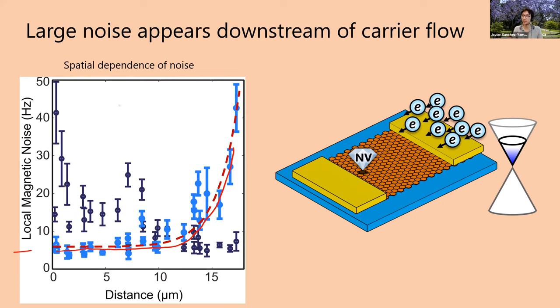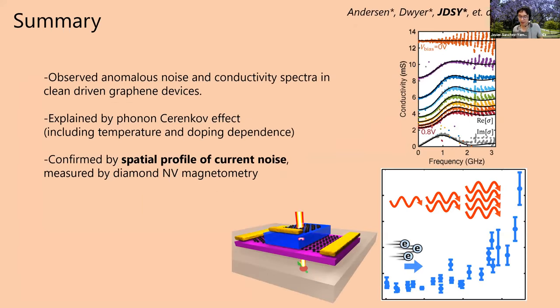And this we could uniquely do because of having this nanoscale magnetometer, which can measure the current fluctuation profile, which is something that really has never been done before, measuring the spatial dependence of current fluctuations. Okay, so that ends my talk. As far as NV magnetometry is concerned, we observed this anomalous noise signal, which we ascribed to this phonon-Cherenkov amplification effect in graphene. And we were able to measure its details by looking at the spatial profile of the current noise.